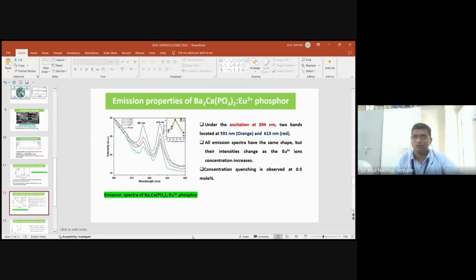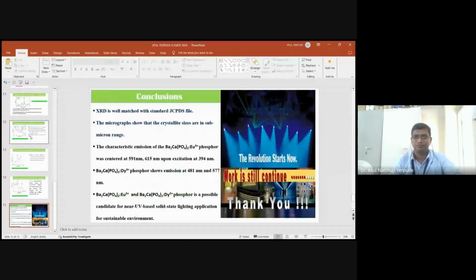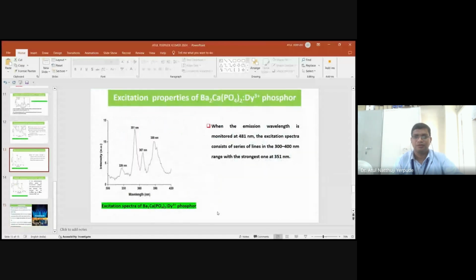We find out the concentration quenching is observed at 0.5 mole %. This one is the excitation spectra of the barium calcium Dy3+ doped phosphor. This excitation spectra consists of a series of excitation peaks, having the peaks observed at 300, 326, 351, 367, and 380 nanometer.